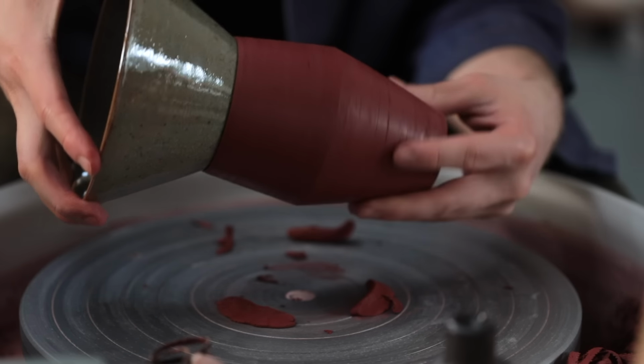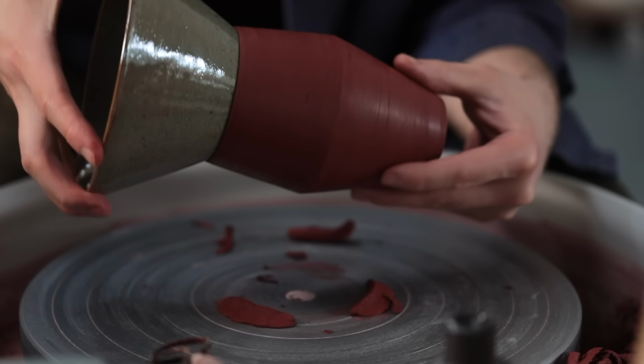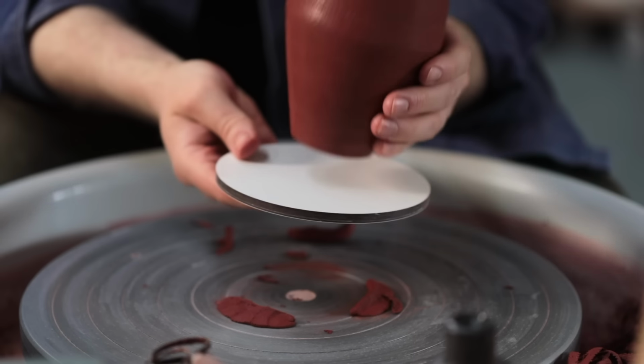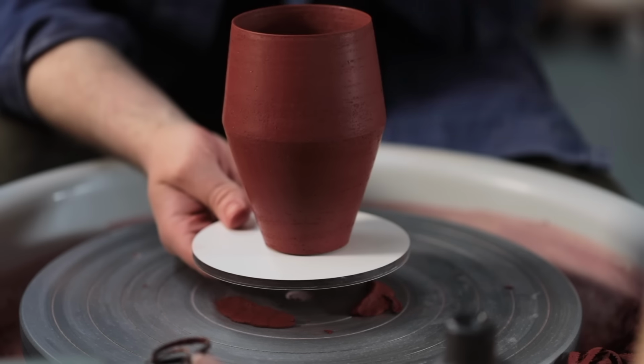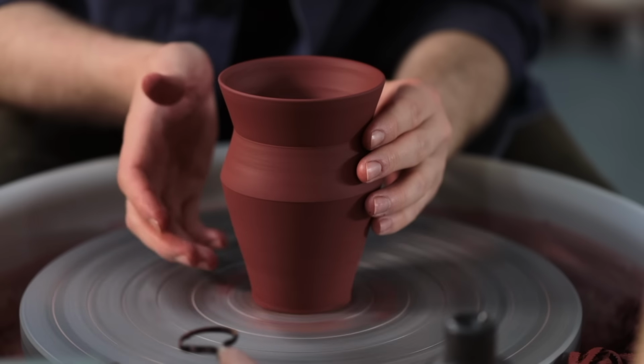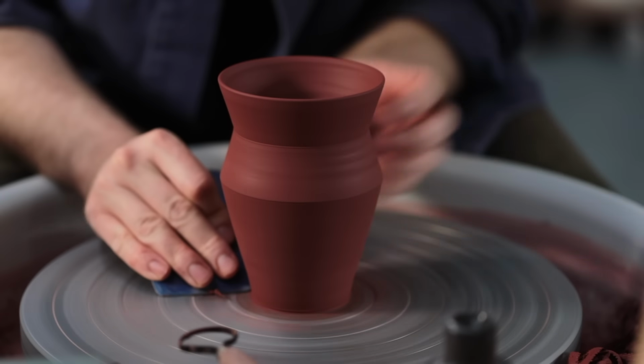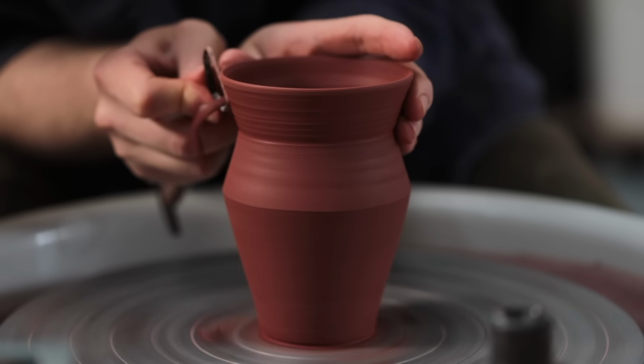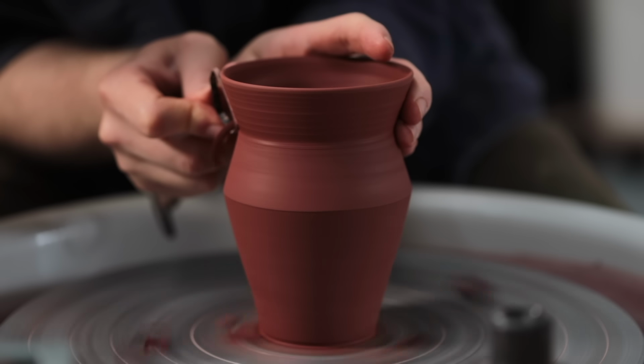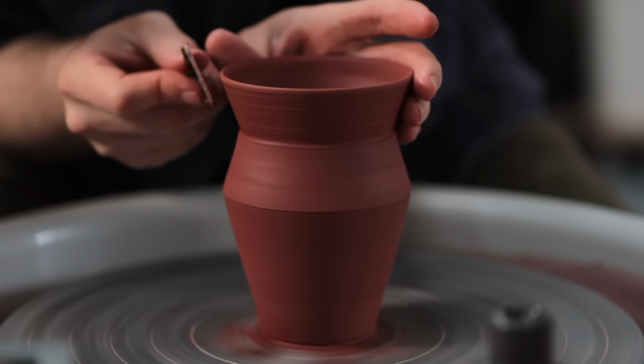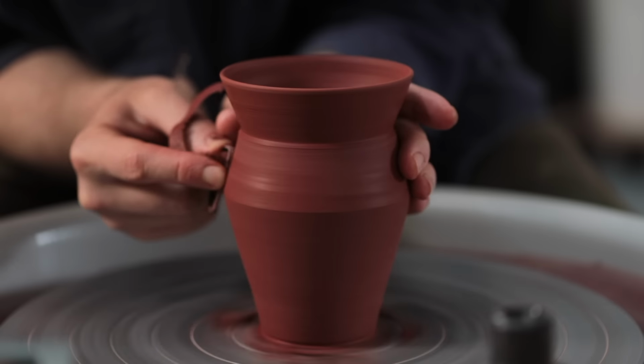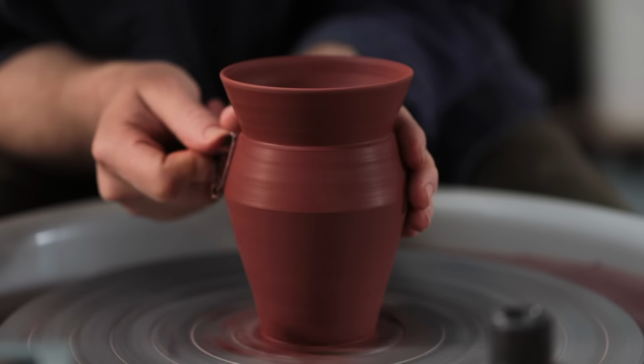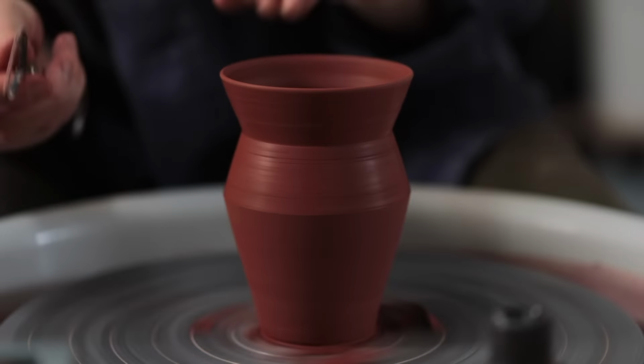The last thing I do is insert a round pot into the opening and twist it about a few times. This just ensures that the rim itself is lovely and round too. And for this process, I'm not using my tungsten carbide blades, as they tend to rip and tear through the clay, leaving a surface that looks scratched, whereas these steel tools, that are much more blunt, leave a surface that's burnished and smooth.